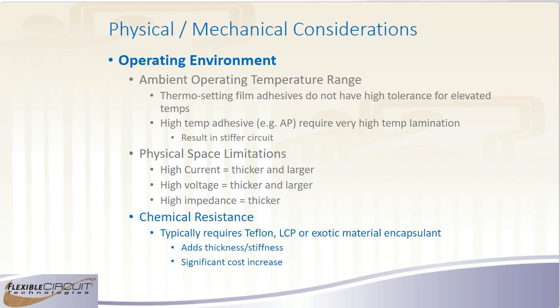Chemical resistance: polyimide for the most part is pretty darn resistant to most chemicals. Its weak spot seems to be alkaline solutions if they're a very strong alkali. And from a saltwater perspective, they're not great for long-term salt exposure. Typically, if you have those types of things or other chemicals that do attack polyimide, you're going to have to put on a cover like a Teflon or LCP over the top of your existing cover. And again, those are difficult to work with.